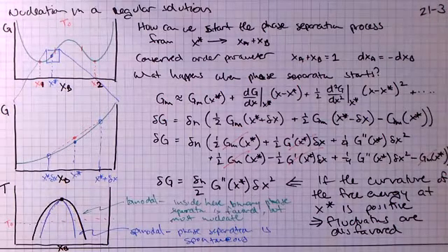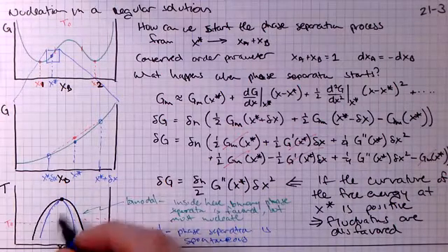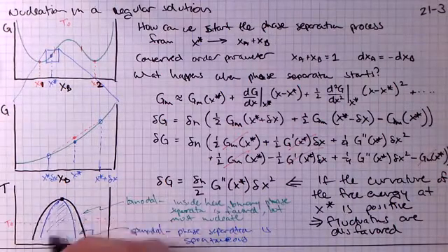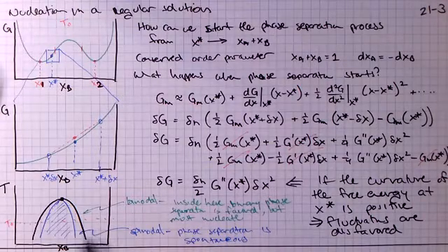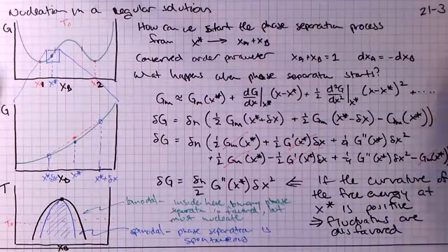And so this is known as the spinodal region. If you go past the spinodal, you're in the spinodal region, you'll get spontaneous phase separation. If you're within the binodal but not yet within the spinodal, you have to wait some time to get a big enough fluctuation so that you can create the phase separation. And this is all without considering the effective surface energy so far.